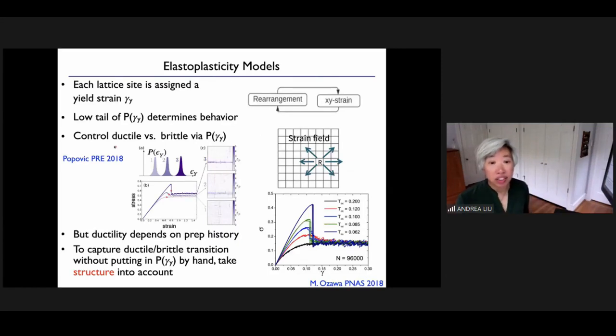There's very nice work from Popovic's group a few years ago, where they showed that if you take an elastoplasticity model, and you assign each lattice site in this model a yield strain, it's really the low tail of that yield strain distribution that determines whether you see brittle or ductile behavior. So if you put in a yield strain distribution that looks like this light one, you see ductile behavior. And if you put in one that looks like this dark one, you see a large stress drop and brittle behavior.